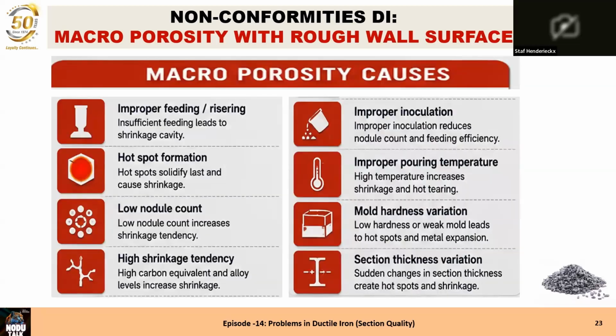If we make an inventory of possibilities, it's improper feeding and risering, of course. That's the main root cause of a macro porosity defect. It's in a hot spot. When we have a hot spot, many times the hot spot is not connected with the riser. If it's not connected with the riser, it can have this type of defect. A low nodule count will also increase this shrinkage tendency, while a low nodule count indicates a low feeding capability, and then it will increase the tendency. With high shrinkage tendency, high carbon equivalent and alloy levels increase the shrinkage, but this is not with a rough surface, it will then get a smooth surface, but I come to that later. Improper inoculation, of course, will give you a low nodule count, and a low nodule count increases the tendency.